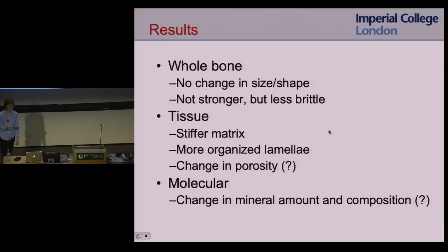What was surprising was that we found bigger differences in the female mice than the male mice. And we weren't expecting that because we didn't find that at the whole bone level. So we didn't expect it, as female mice didn't get fewer fractures than the male mice. But at the molecular level, it seemed like there was a bigger impact on the mineral for the female mice. Which is interesting, because all the stem cells that were injected were female stem cells.